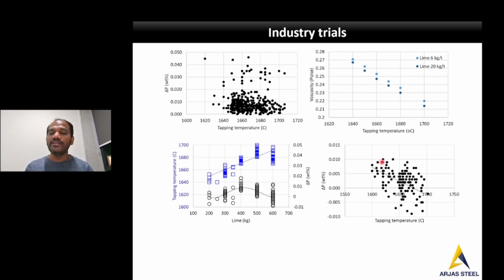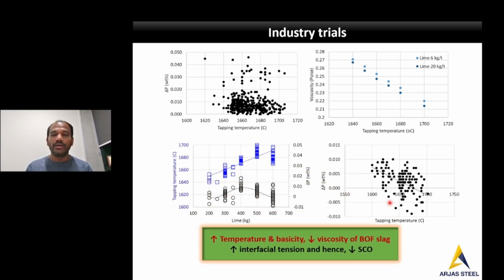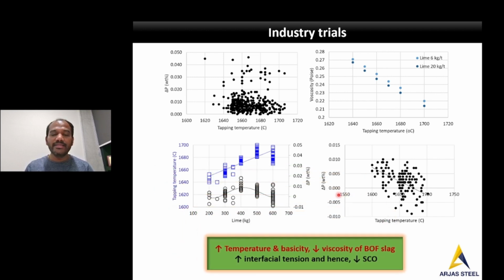And altogether, for a 1 month trial, we could see the phosphorus reversion is very much in control. You can see it is always less than 100 ppm. I can say till date getting less than 100 ppm phosphorus in the crude steel is a challenging task. But we were able to get consistently less than 100 ppm for all the grades after adopting this practice of slag engineering to control the slag carryover. So the learning is that increasing the temperature and the basicity decreases the viscosity of the BOF slag. That increases the interfacial tension, and hence the slag carryover decreases.